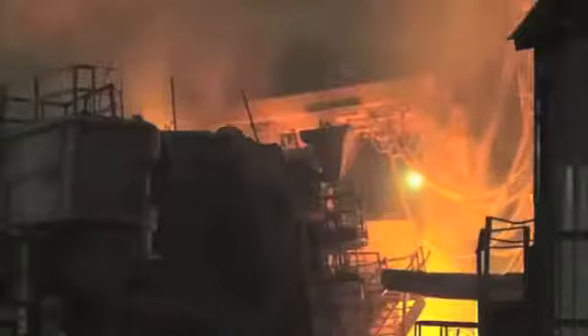Once the scrap and pig iron are loaded, the roof of the furnace is closed, and 3 large carbon electrodes are lowered through an opening in the roof. Then, it's showtime. And it's loud, very, very loud. The rods circulate or arc up to 115 million watts of electricity to melt the scrap at a temperature reaching 3,000 degrees Fahrenheit. The power is on for about 35 minutes to complete the melting of each heat, which is a good reason why our monthly electric bill is about $7 to $8 million.